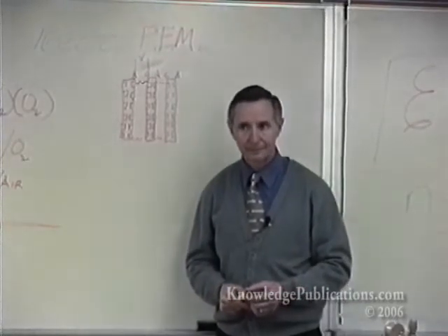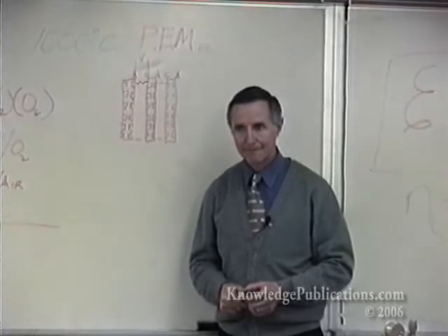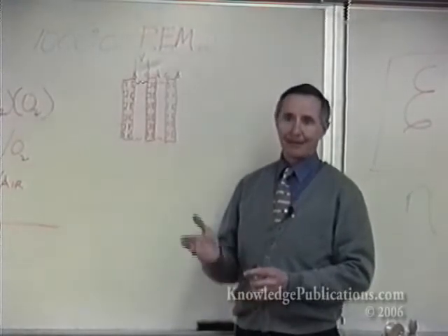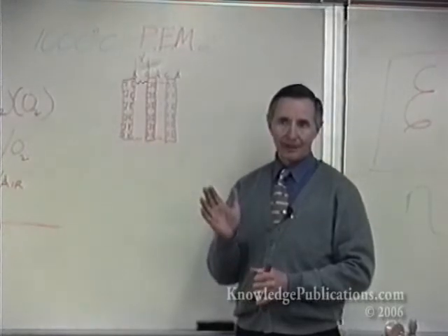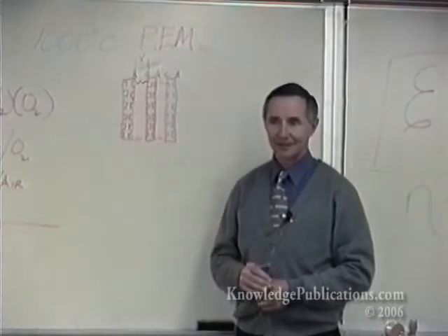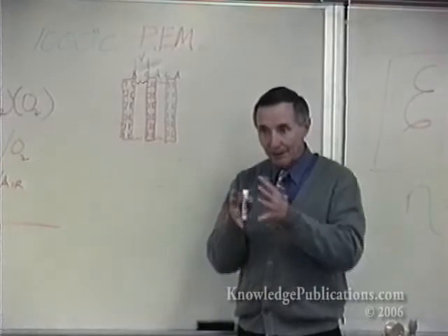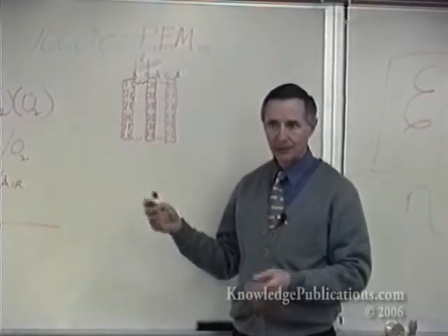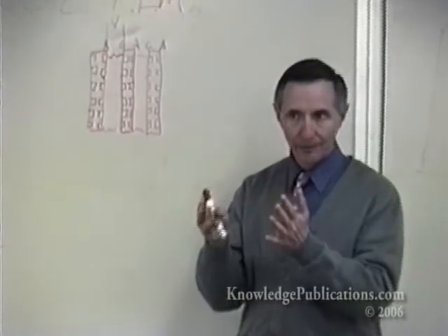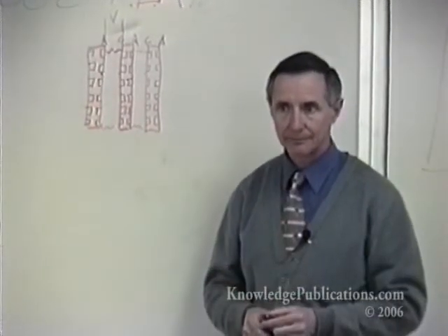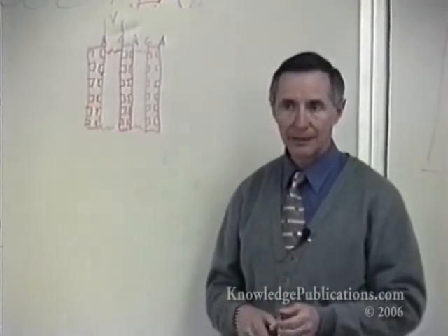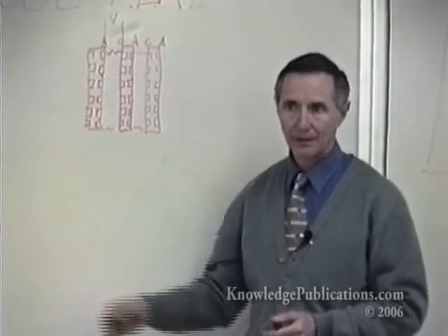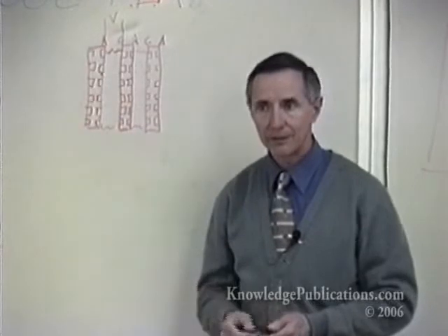Will Teflon ever work in systems like that? I mean, it's probably not porous. You build it out of Teflon powder, and you build into it the pathways for ion exchange, and you fuse it to make it impermeable to the gases. Or you build it out of a solvent that precipitates the film, and you evaporate the solvent and recover it.